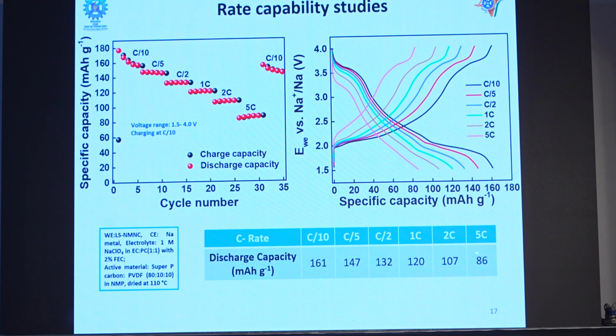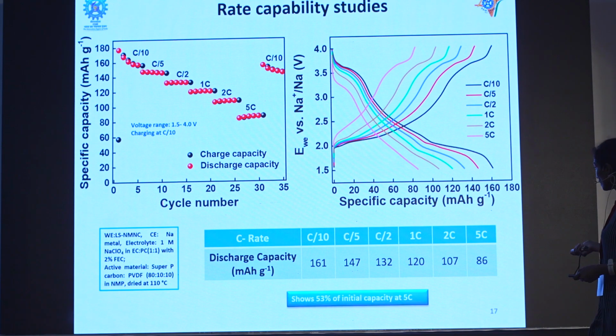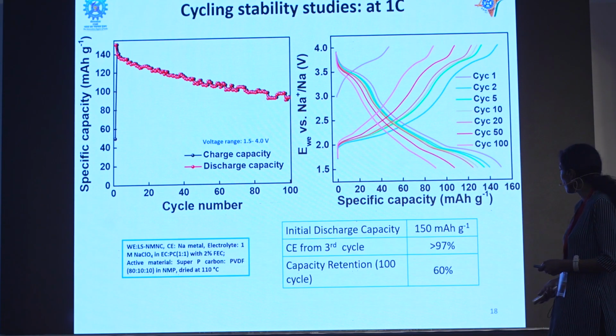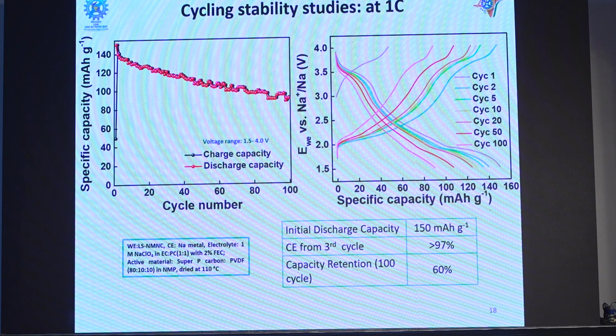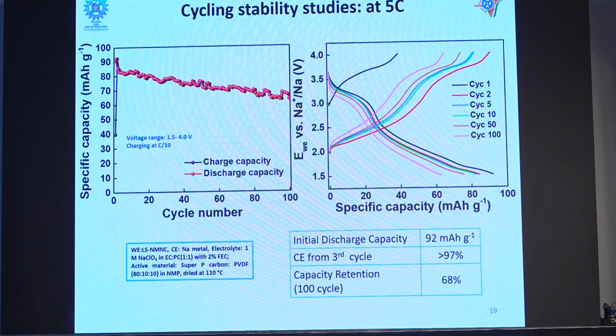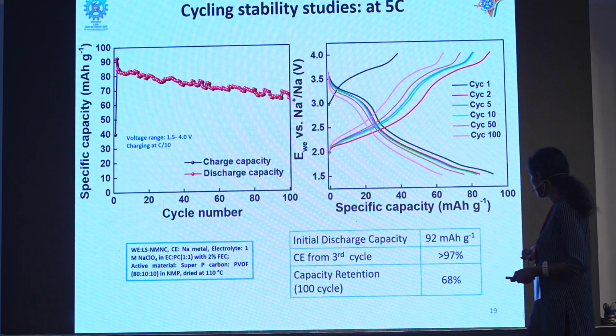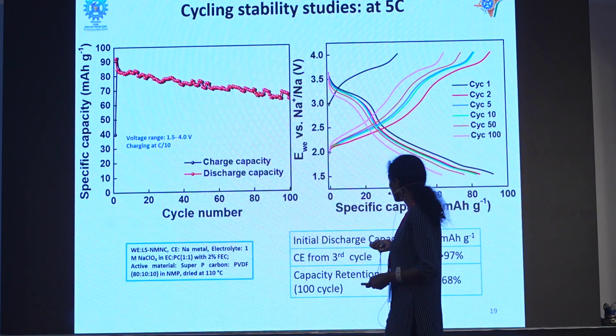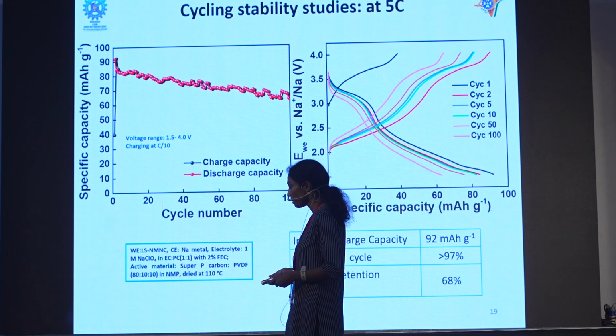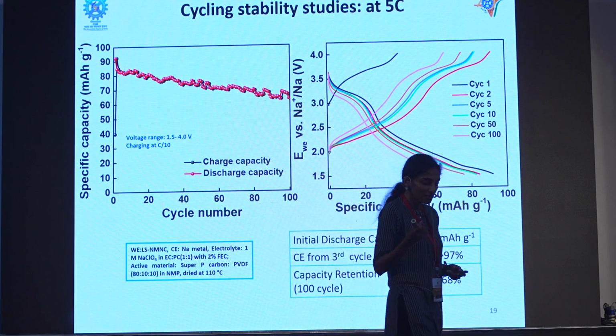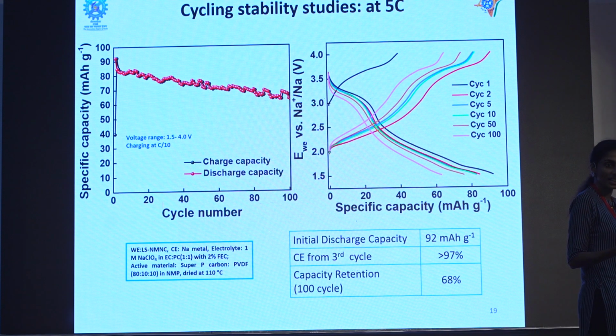In 6 minutes we are getting approximately half of the capacity we got when we charged and discharged the battery in 10 hours. So this is a good observation, and then we wanted to cycle the battery at higher current rate, that is at 1C and 5C. At both 5C and 1C, we are getting a good capacity retention, and the initial discharge capacity is about 92 milliampere hours per gram. So this material has a better cycling stability than its parent compound and a better rate capability than its parent compound.